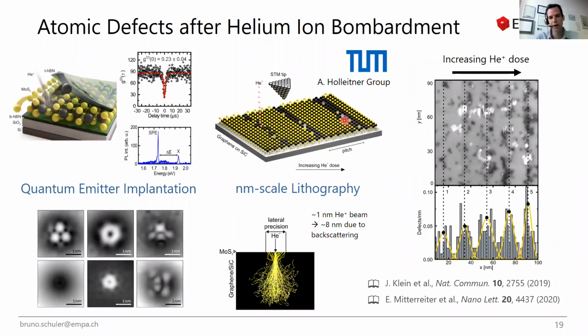Then another thing we have tried, in collaboration with the Holleitner group in Munich, and Elmar Mitterreiter actually came to Berkeley and did these measurements together with us, is to bombard, in this case, molybdenum disulfide with a helium ion beam, to really try to lithographically define defect patterns. That's what should be shown here. Elmar wrote lines with a certain spacing, I think 20 nanometers or so. And we could indeed see that in a certain direction, we have this line-looking structure.